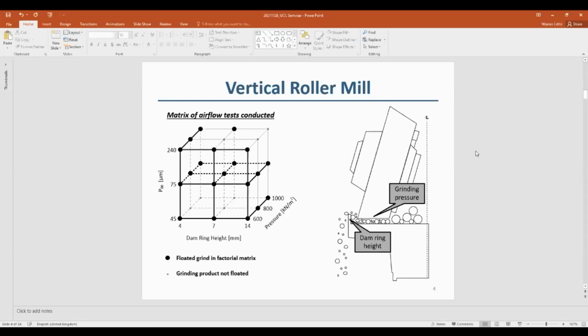Also changed the grinding pressure, so the forces that the grinding rolls exerted on the material, as well as changing the target P80. Targeting a P80 was achieved by varying the dynamic air classifier rotor speed. So we kept pressure drop and airflow rate across the mill constant. Just varied the dynamic air classifier rotational speed until we achieved the product P80 we needed.